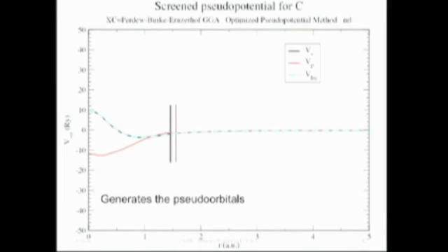but there's one bit here that makes life difficult for everyone, and that's the fact that different angular momentum channels, S and P here, have different potentials. This is a so-called non-local pseudopotential. I'll say more about it in the remaining couple minutes, but that causes us all kinds of headaches. And if you try to do this with just a single potential that represents all of the angular momentum states together, it's just not accurate enough.